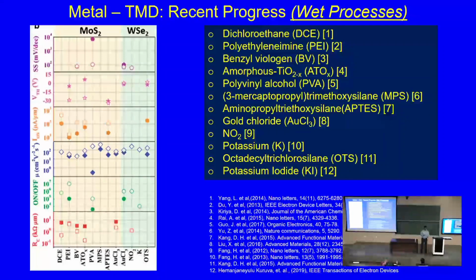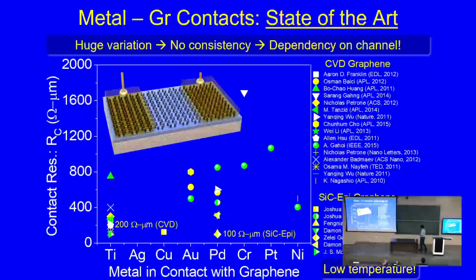So while I can demonstrate contact resistance being lower, at the next step the contact is gone, right? It's again back to the normal, back to that high resistance state. So while there are a lot of papers, all these papers are useless, just because I cannot adopt it in an industrial scale solution. So this was the state of the art.